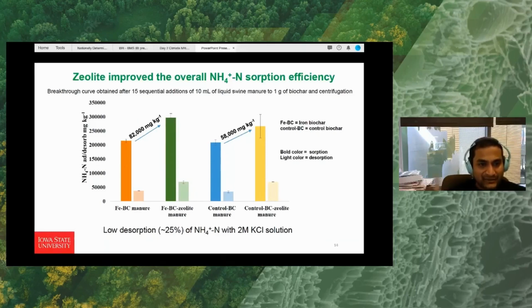And we did the desorption from there, and we found low desorption of ammonium nitrogen from the system using 2 normal KCl solution. So this slide suggests that zeolite can improve the overall nitrogen absorption and lower desorption of ammonium after the total system analysis. Next slide, please.